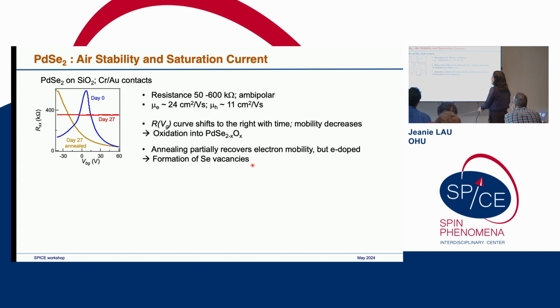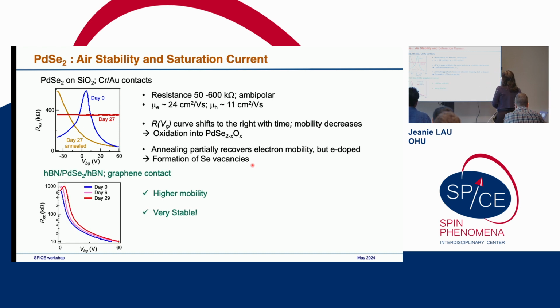So we can anneal it. The nice thing is that we can anneal it. So this is after annealing. It does recover the electron mobility, but it becomes very strongly electron doped. I think it's probably a formation of selenium vacancies. And what happens if you leave it outside in air, we believe, is probably partial oxidation. Of course, if you put it between hBN, and we have graphene contact, it's much nicer. So we have a very high mobility, and this is very stable.